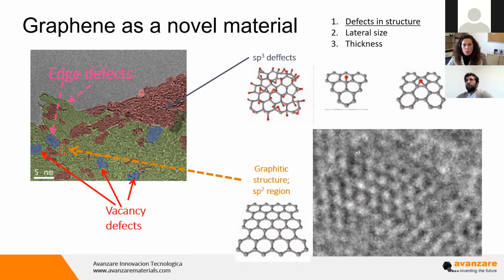The defects can be due to sp3 hybridization because of oxygen mainly; it can be other atoms, but mainly it is oxygen. In this case, the carbon is not in sp2 hybridization, but sp3. So this is blocking the movement of electrons and phonons. Also, we find the ends of the layer, which are defect positions. And also there are areas where there are no carbon atoms, which are vacancy defects. So regardless of the type, all these defects are affecting the movement of electrons and phonons, and thus decreasing the thermal conductivity, and also the electrical, but in this case we are focusing on thermal.